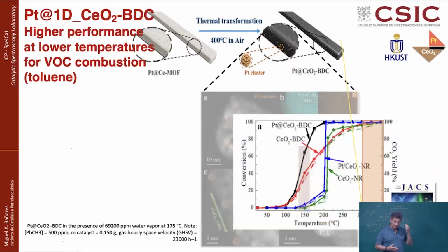And the performance of this material is very good. You can actually observe how this platinum on the ceria oxide that derives from this benzene dicarboxylate metal organic framework is converting toluene very efficiently to CO2, even at 200 degrees C and above. If you only use the nanorod that derives from this MOF, you also get quite a good performance, but not that good. You have to go close to 300 to get a total combustion, which is telling you that indeed the interface between platinum and cerium is really promoting something special in the system.